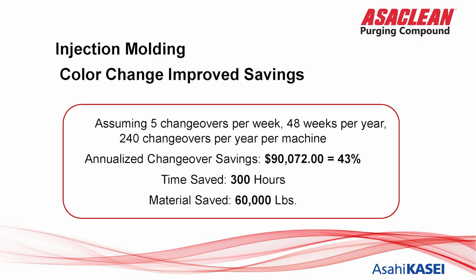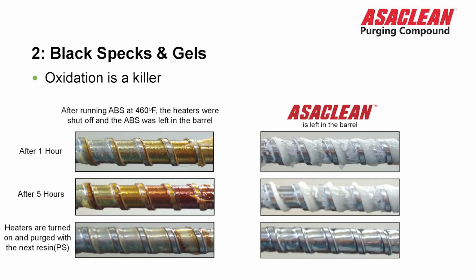So you can see where purge compounds can have a huge effect on your bottom line. Second thing, black specks or gels. These pictures depict what happens if you were to leave ABS in your system at 460 degrees for a period of time. You can see after 1 hour, the ABS begins to degrade pretty well. After 5 hours, it's pretty well gone.